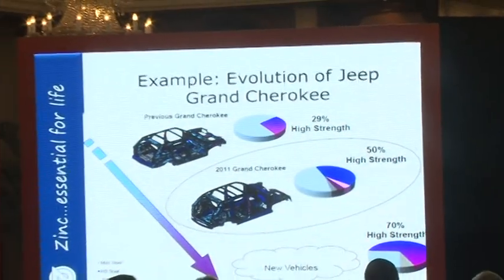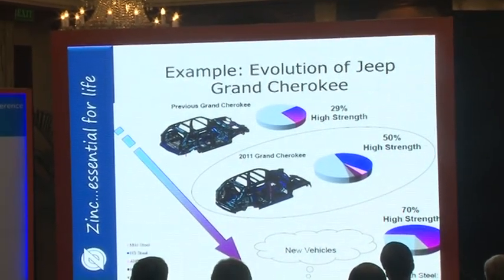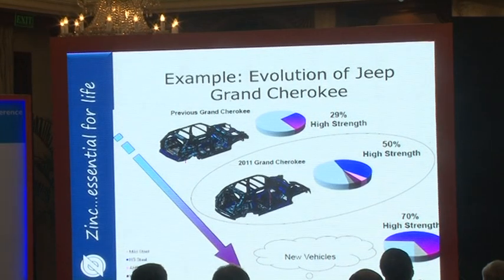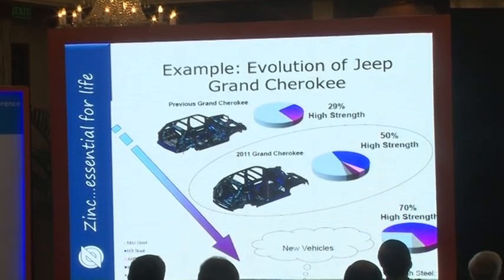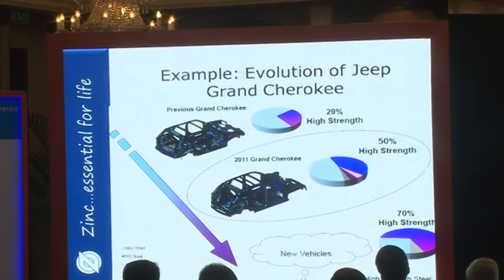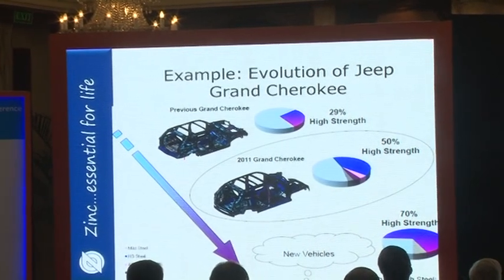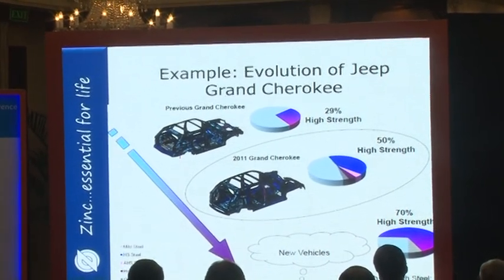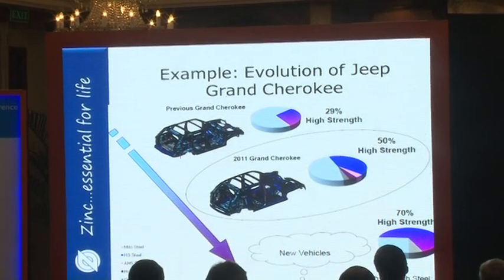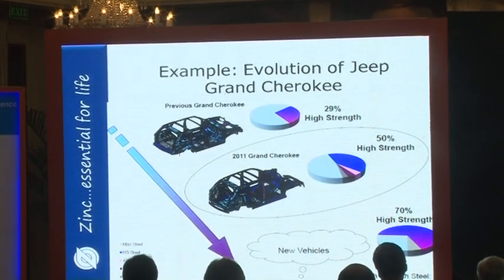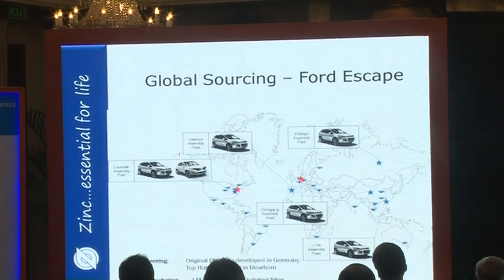And this is an example in the USA. We have the Jeep Grand Cherokee automobile, which was 29% high-strength steel in the mid-2000s, going to 50% high-strength steel in the 2011 Grand Cherokee, and moving up to 70% as we go further into this decade. So this is just one example. We have many cars that are in this situation adopting these higher-strength steels, consistent with what's been said before.